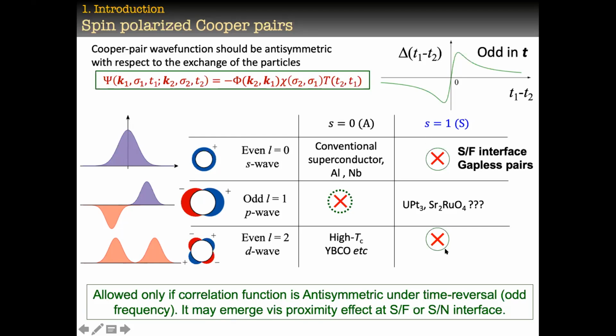But this kind of situation, where we will utilize the time reverse symmetry, or you could say that the time is antisymmetric, this time is odd. So in that case, we have to break some symmetries, and that could be possible if we have interfaces between superconductors and some other special materials. For example, the S wave triplet superconductivity we can achieve at an interface of a superconductor and a ferromagnet.